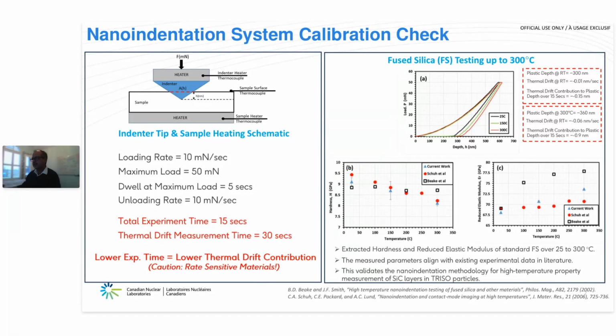So the total experiment time to load, hold, and unload was 15 seconds for these experiments. For the thermal drift measurements at the end of the experiment, we held the indenter tip barely touching the sample, at 10% of the maximum load as specified by Micromaterials, for 30 seconds. In the box on the top right, you see the load displacement curves from room temperature to 300 degrees C for fused silica. As expected, the displacement at the maximum load of 50 millinewtons increased with the increase in temperature.